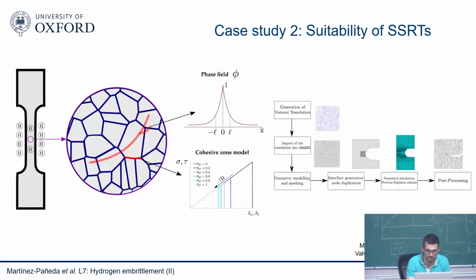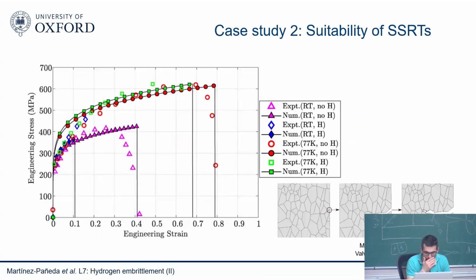Yeah. And then the last part of this study that we were looking at is a slightly different problem. The group at the University of Virginia did some experiments, again with SSRTs, but that's not relevant here, on nickel. They were trying to bring some light into the debate. In hydrogen, there's always this big debate about the mechanism. Some people argue whether it's a decohesion-driven mechanism or a plasticity-driven one, maybe a combination of both, and that can change with environment, with the material, and so on.